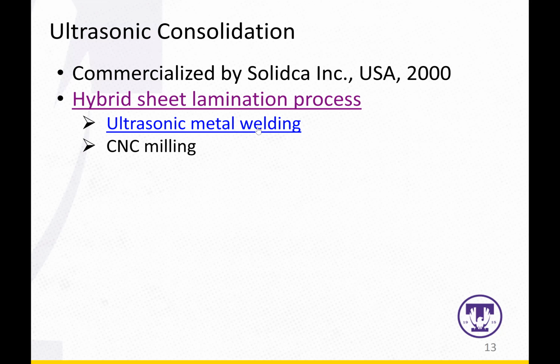Ultrasonic consolidation produces direct metal parts from CAD data by ultrasonically welding layers of coiled aluminum foil strips to a prepared metal substrate. As the foil strips are placed on the substrate, a tool called the sonotrode uses high-frequency vibratory energy and moderate force to disrupt the interface surfaces, inducing interatomic attraction and metallurgical bonding between the foil and the substrate surfaces. Once ultrasonically welded, the layer is then milled to the cross-sectional shape defined by the CAD data.